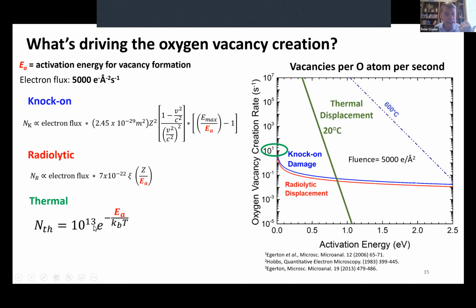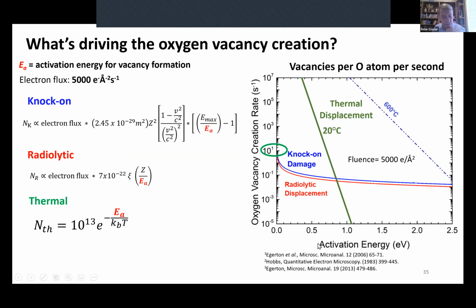Now, if you go to the thermal processes, the number of vacancies created depends on this Arrhenius expression here. I'm sorry, maybe you can't see this. It's e to the minus EA over kT. So that has a much stronger dependence on the activation energy. That's what this green curve is here. In this case, it's evaluated at room temperature. So you can see that as the vacancy formation energy decreases, you see this enormous increase in the number of oxygen vacancies created.